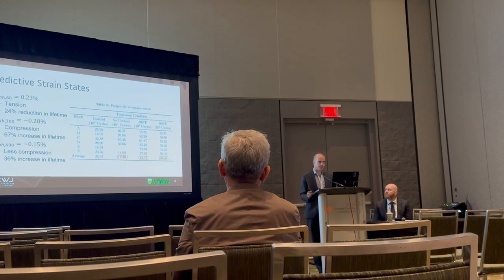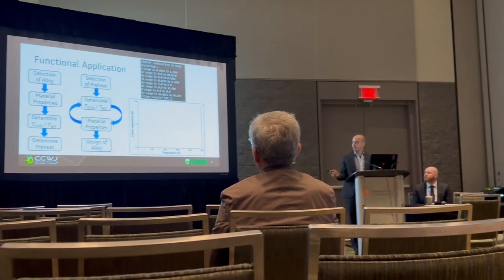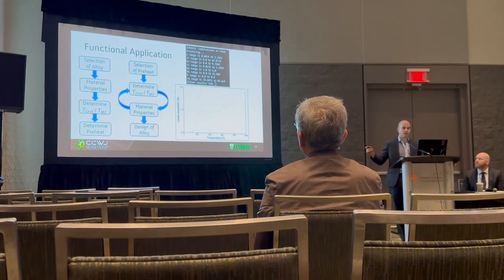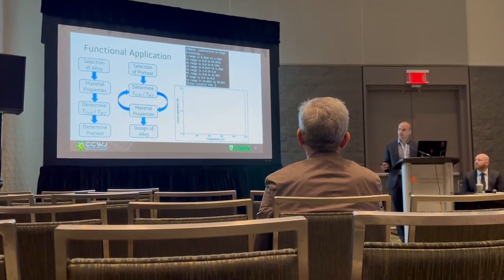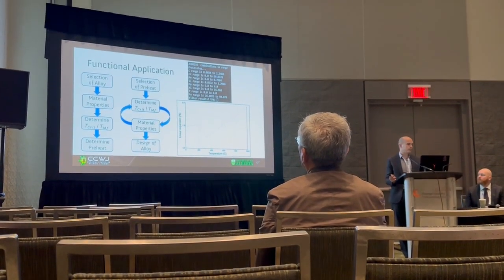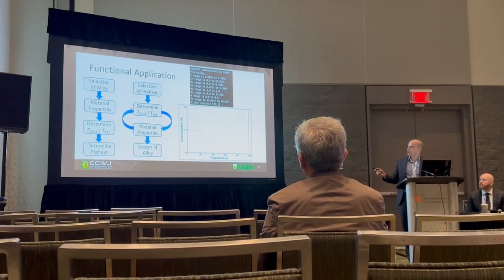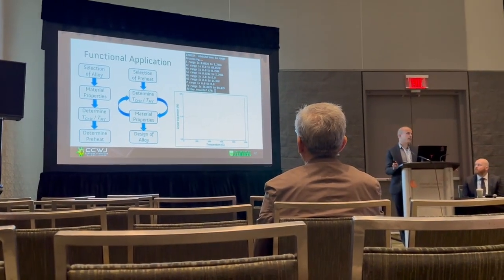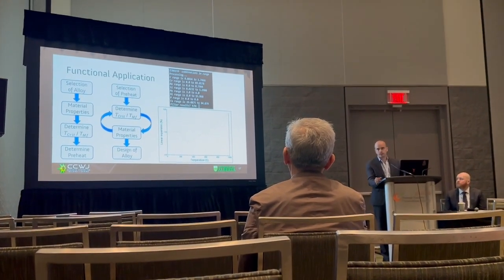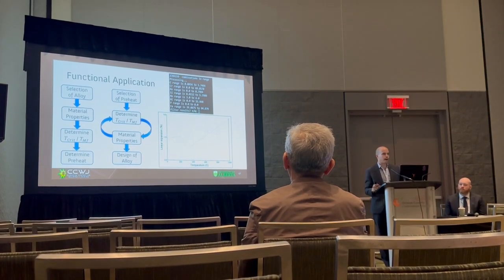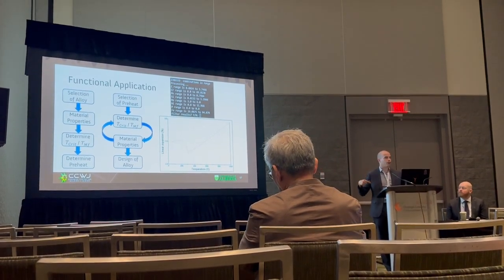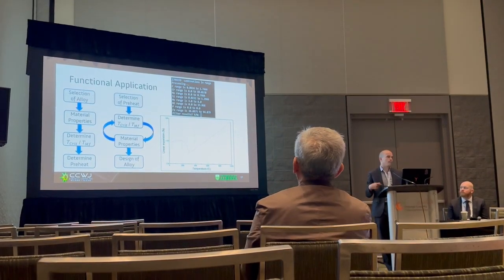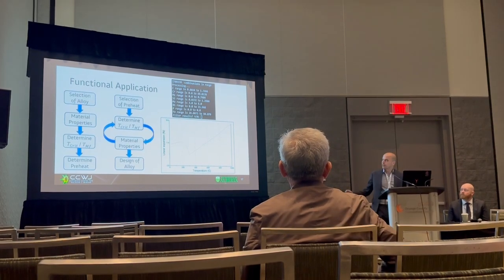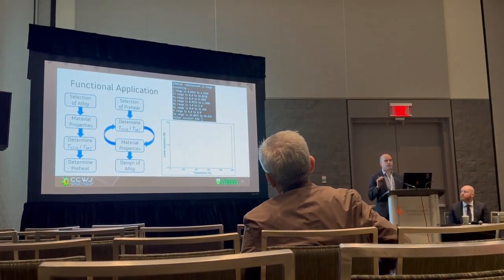So then to bring it back to my train wheels, now that I validated that there seems to be something here that's working, we went to the train wheels. So this is how I actually apply this model when I'm designing things for these wheels. There are two design routes you can take. The one I'm using is over here, and we can't preheat a half ton of steel effectively. If I wanted to weld repair all 8 wheels on every car of a 100 car train, I'm not preheating all of them to 300 degrees. So I have no preheat. My selection of preheat is room temperature.